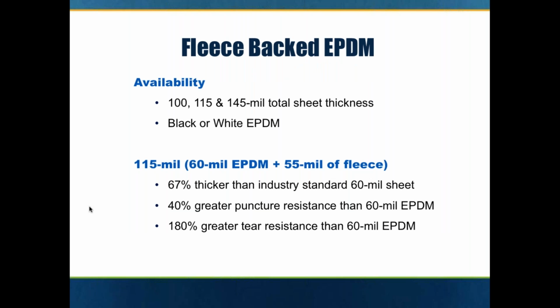So Fleeceback EPDM is available in 100 mil, 115, and 145 mil. That includes the 55 mil fleece thickness, and that is available in white or black. So with the 115 mil, there are some tremendous attributes: 67% thicker than the industry standard 60 mil, 40% greater puncture resistance, and 180% greater tear resistance.